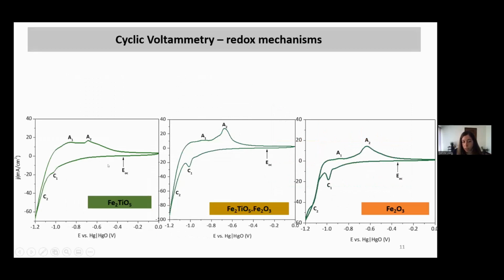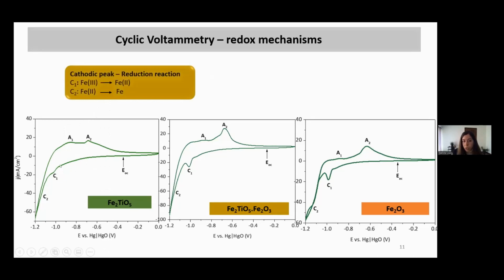These are the cyclic voltammetry results. These give us really good information about at which potentials we have redox reactions occurring. So as you can see, we have two C peaks, cathodic peaks, and two A, anodic peaks. The cathodic peaks are associated with the reduction reactions. So first peak, we have reduction of iron 3 to iron 2 species. And the C2 peak is not properly a peak, it's more like a shoulder. It's the reduction of iron 2 to metallic iron. However, this is exactly the region where we have hydrogen evolution. So that's why it competes for the cathodic current, because it occurs at exactly the same potentials.